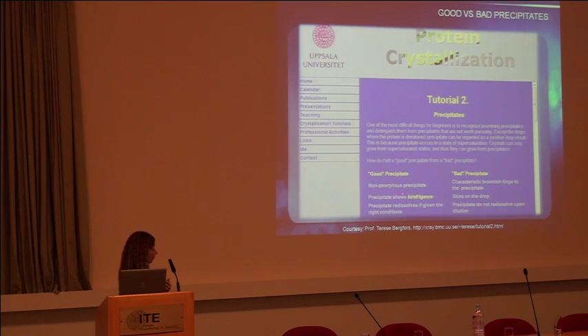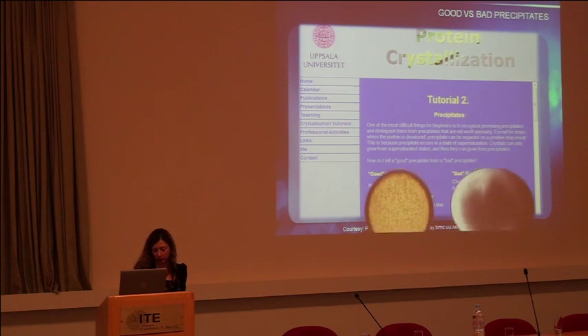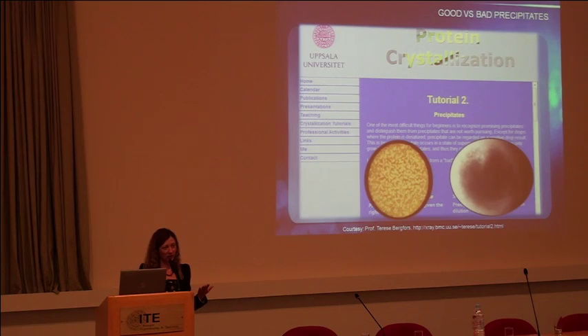The good precipitate is non-amorphous, is microcrystalline. Sometimes it's nanocrystalline and you cannot see the crystals with an optical microscope. It shows birefringence, and the precipitate redissolves if given the right conditions. The bad precipitate is amorphous, it's brownish in color, it creates skins on the crystallization drop, and it does not redissolve upon dilution. So if we look at the two cases with an optical microscope, this is how they look. From the optical microscopy figures, if it's shiny, you can be hopeful that it's microcrystalline and not amorphous.